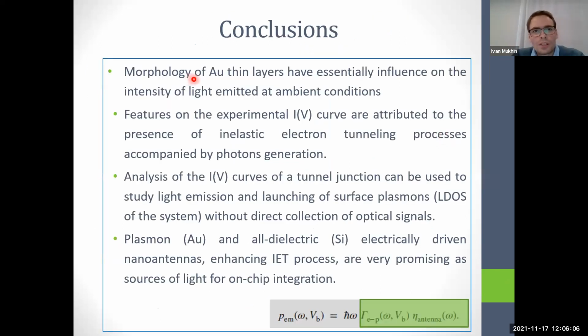I would like to point out that the morphology of thin layers of gold is essential for light emission. Features on experimentally obtained IV curves are attributed to the presence of inelastic electron tunneling. And in order to study the local density of states of your nanosystem, you don't need to collect light. What you really need is to analyze IV curves. Plasmonic nanoantennas, as well as hybrid silicon material, can produce electrically driven nanoantennas, with the efficiency of the electron tunnel process enhanced by optical states of the structure. Thank you very much for your attention.